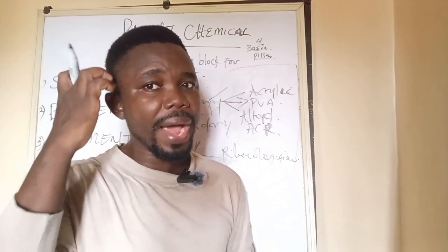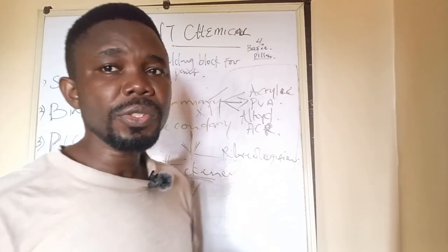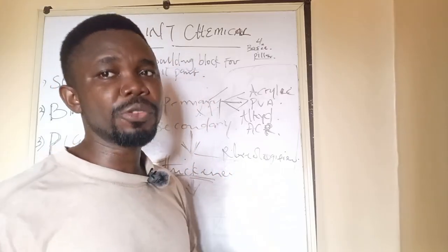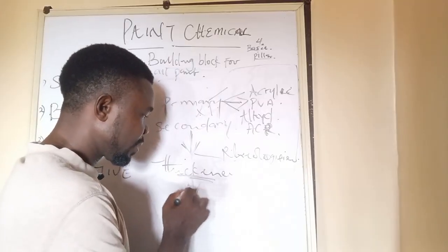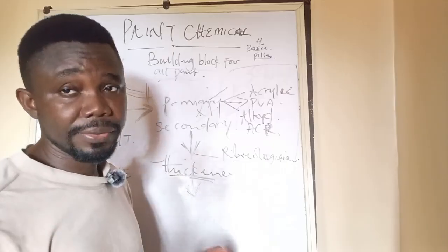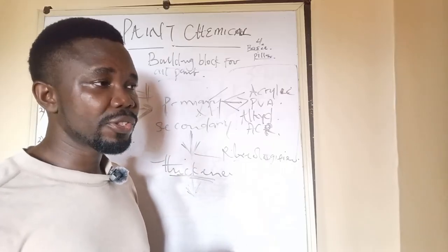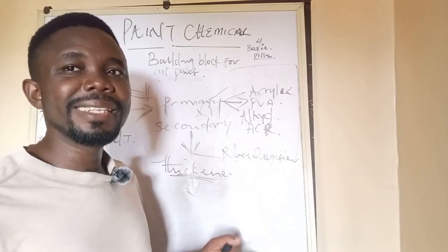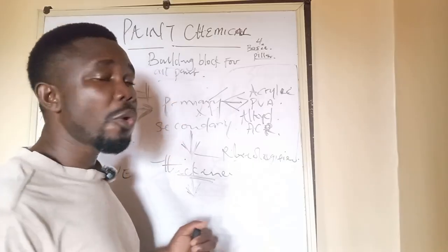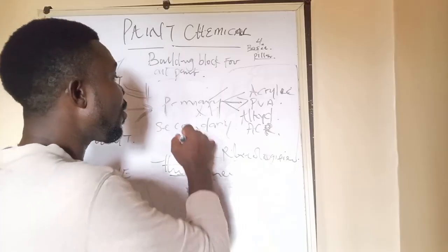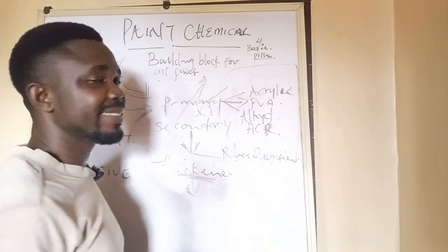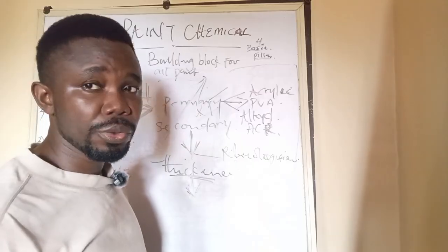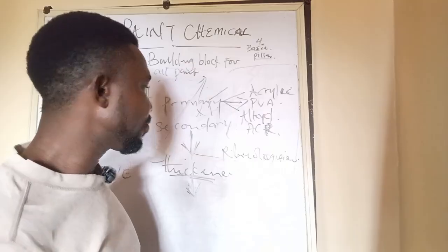That is the reason why, if your paint starts settling after you produce, your secondary binder is failing. Your thickener is not enough. That's what it means. Your thickener is not enough to carry the weight, or to hold together all of your agglomerates, especially the pigments that you use, which includes your filler and every other thing.